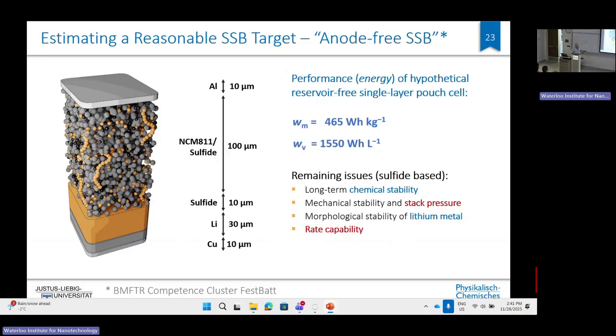Lithium was brought into the cell. It was not fully reservoir free, with 30 micron lithium, current collectors, and a rather thick cathode. And then you can achieve 465 watt hours per kilogram on materials level. There's no housing around that yet. That's not calculated. So with the housing, we may still be a bit below 400 watt hours per kilogram. But you see how difficult it is to really climb up. You have to fight by proper engineering at every corner of your cell to get values that can surpass a lithium-ion battery. So working on solid-state batteries, every day I think, okay, engineers really did so well with liquid-based batteries to achieve the numbers we achieve today.